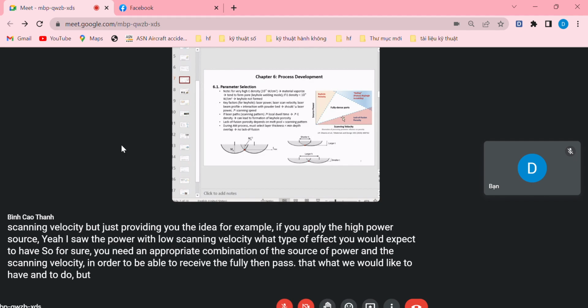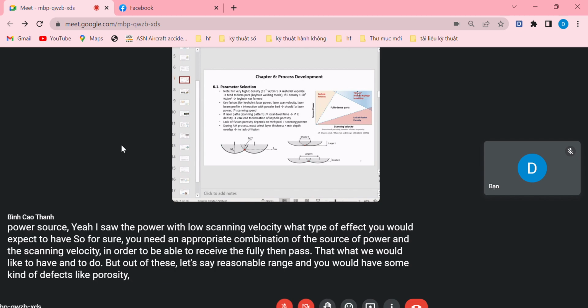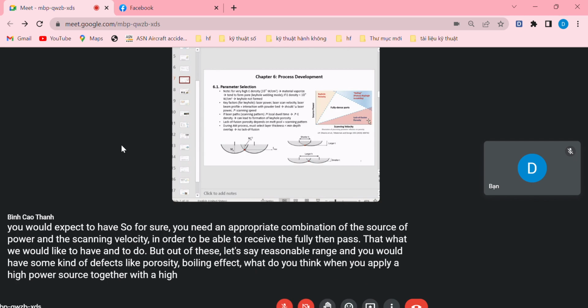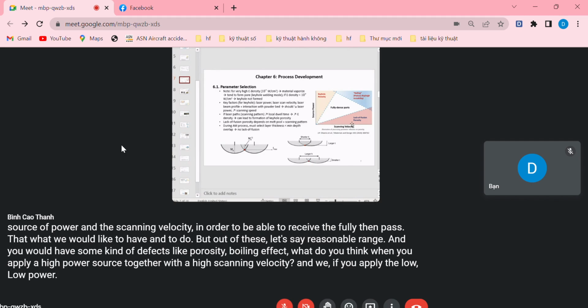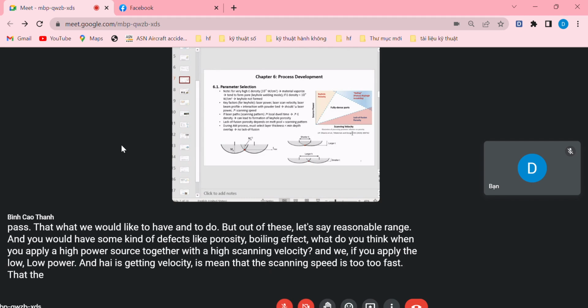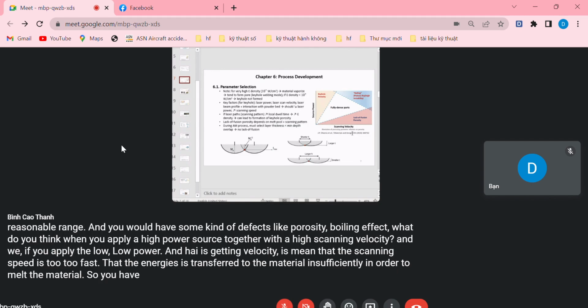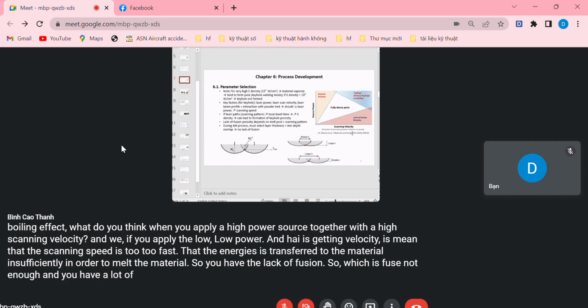But out of this reasonable range, you would have some kind of effects like porosity, or the balling effect. Balling effect occurs when you apply a high power source together with a high scanning velocity, and if you apply low power and high scanning velocity, it means that the scanning speed is too fast, so the energy is transferred to the material insufficiently in order to melt it. So you have lack of fusion, which is fused not enough, and you have a lot of porosity between the powders.